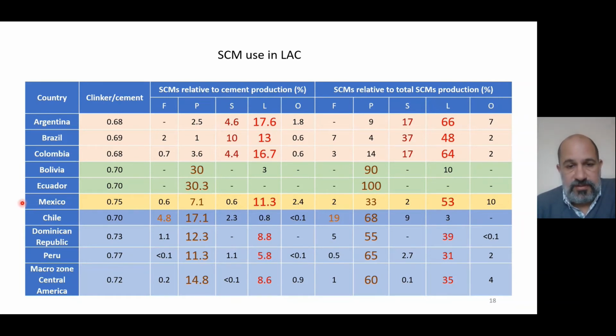We have Mexico as a special case, in which limestone and natural pozzolans are quite evenly used, but not in as high percentages as in other countries. And here the clinker factor is slightly higher than in the rest of the region. The same happens for Peru, which has one of the highest clinker factors in the region. Chile is another special case. It's the only country where fly ash has a significant participation as SCM in cement. Maybe it's only comparable to Brazil with 2% of the total cement production.